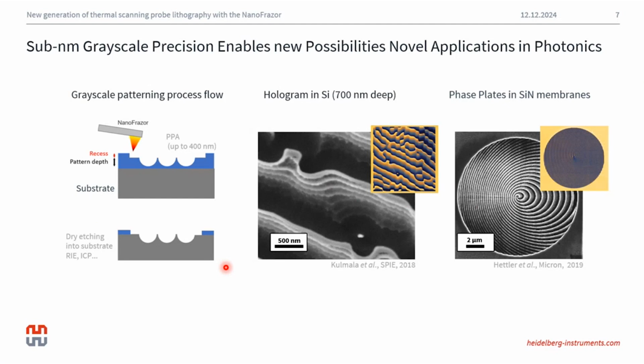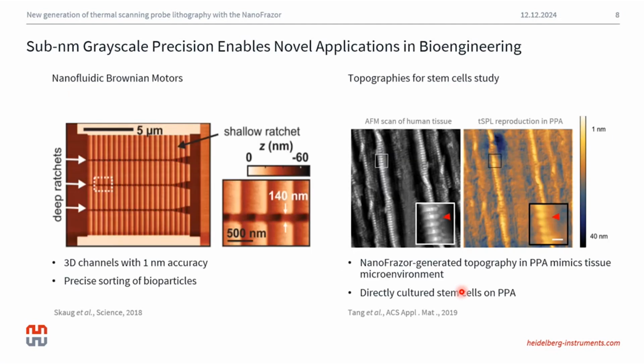So this method, as I mentioned earlier, has proven to be very useful for nanophotonics devices applications, but also for bioengineering applications, where in one case, we've created 3D channels with 1 nanometer accuracy for the precise sorting of bioparticles and the creation of nanofluidic Brownian motors. In another case, we used the topography of a human tissue and replicated it directly into PPA. And because PPA is biocompatible, we were able to directly culture stem cells on top of the PPA surface.